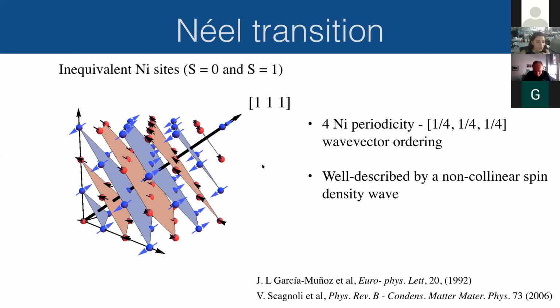So corresponding to the 2 different types of nickel that you have in the insulating phase, and of course all the antiferromagnetic phases inside the insulating phase. You have here, I show blue and red nickels, which corresponds to the charge disproportionation. And it seems that the antiferromagnetic ordering is well described by a non-collinear spin density wave. So that means that as you go along the magnetic wave vector, the spins are not all parallel to each other. In fact, you have these ones which I have drawn out of plane, and then the next ones are in plane, and then the next ones are out of plane.